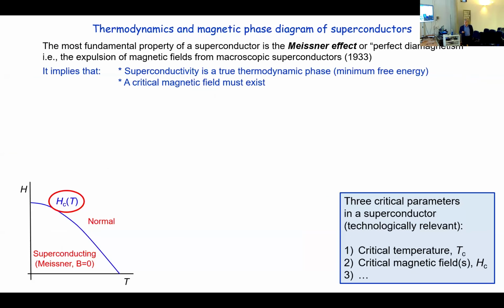So let me go through a little bit of thermodynamics of superconductors. As I mentioned, zero resistance is not the most fundamental property. The most fundamental property is the Meissner effect, or perfect diamagnetism, that implies the expulsion of the magnetic field from inside a macroscopic superconductor, discovered in 1933, which implies that, number one, superconductivity is a true, real thermodynamic phase transition, and consequently is the minimum free energy in some conditions of temperature and field. And second, it implies that there must exist a critical field. So there must be a phase diagram like this, where the material is superconducting below this curve and normal or non-superconducting above this curve.